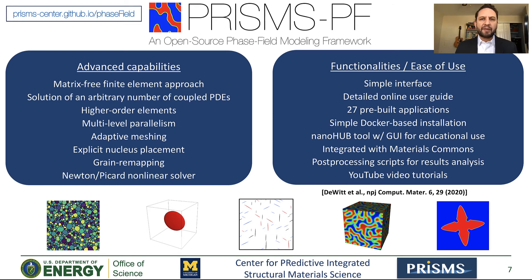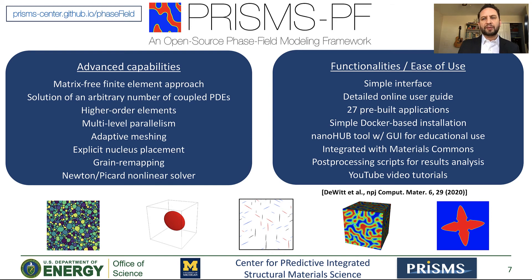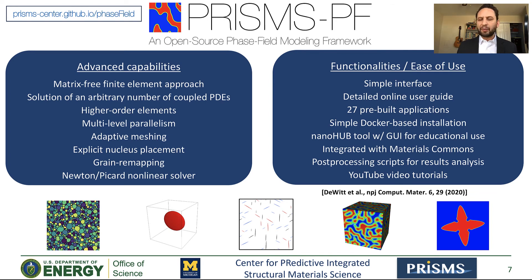We have a method for explicit nucleus placement, based on a nucleation probability function that the user can define. A functionality for grain remapping, which can significantly reduce the computation time in grain growth simulations by assigning a small number of order parameters to track all grains in the system. And a recent capability is the Newton-Picard solver, which allows us to solve non-linear ordinary differential equations at every time step — for example, solving for the equilibrium electrostatic potential as the system evolves.